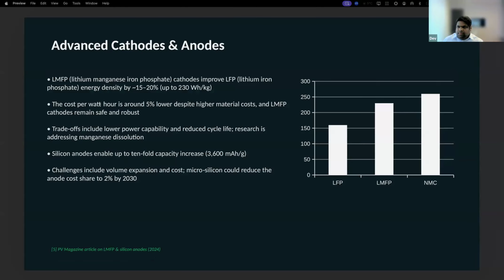So let's discuss a little bit more about advanced cathodes and anodes that are around the corner. This particular slide explores the innovations that push the boundaries of lithium-ion performance. In this one, the LMFP, lithium manganese iron phosphate cathodes, build on the lithium iron phosphate chemistry by substituting some iron with manganese. This increases the operating voltage and thus the energy density by 15 to 20%, reaching up to 230 watt hour per kilogram.